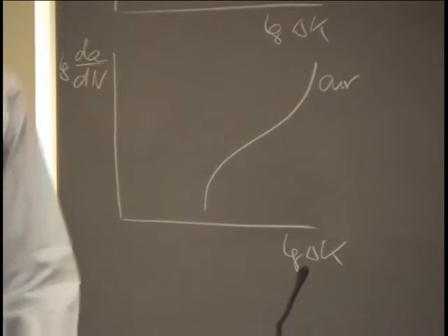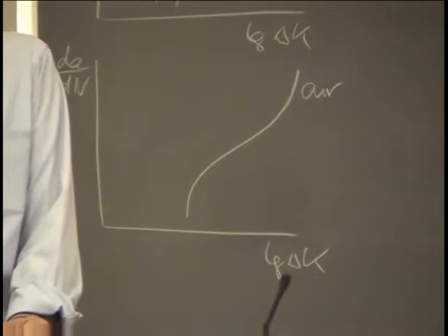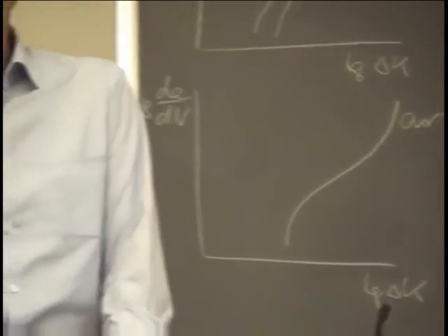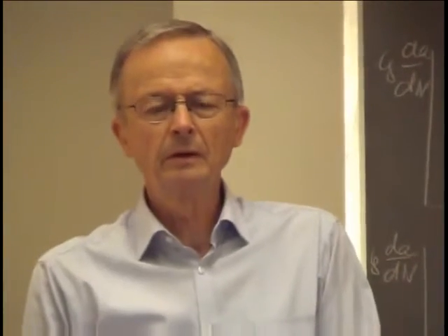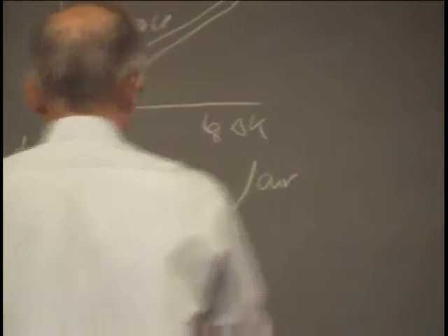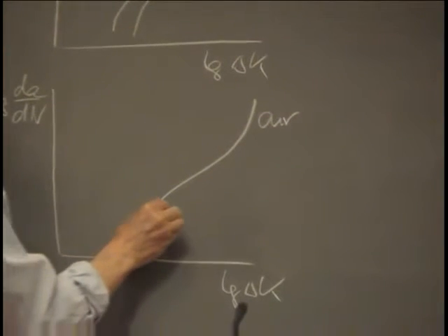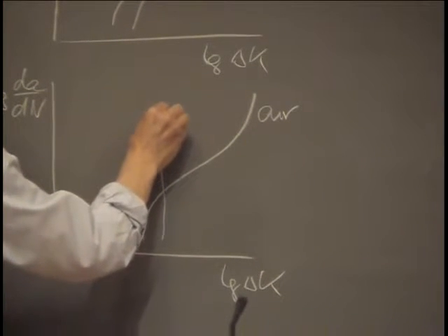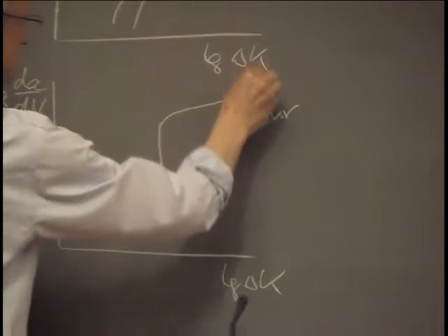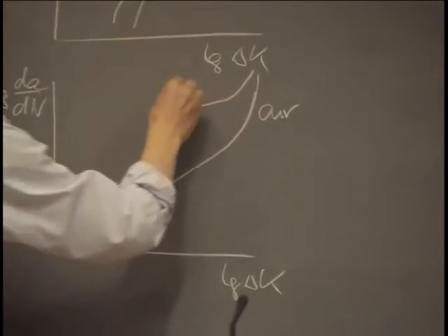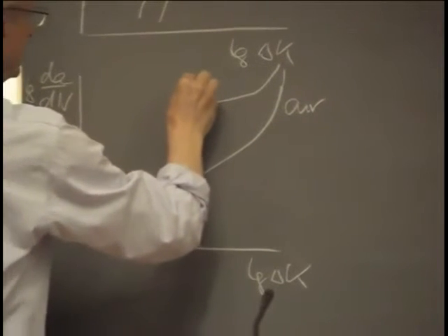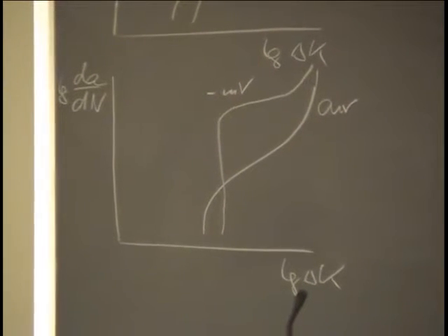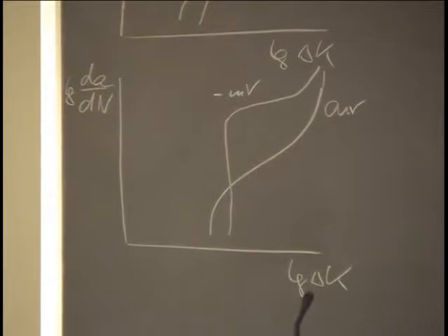And when you do tests in salt water with cathodic protection, something very strange happens. We had a higher threshold and hence lower rates here. And then this happened. Say negative millivolts as a symbol for cathodic protection.